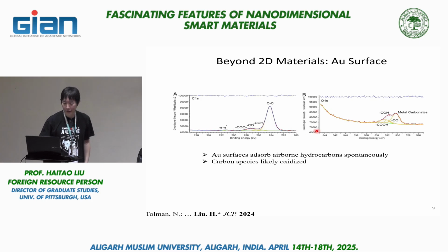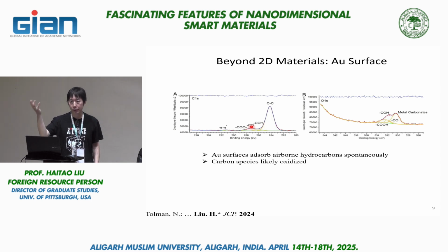This is XPS data again, hopefully you're familiar with this now. It basically shows different kinds of carbon material being deposited on a gold surface. Again, by simply exposing a porous gold substrate to air, we start to collect hydrocarbon from air. And we see both carbon signal and oxygen signal. So again, this shows it's partially oxidized hydrocarbon material.